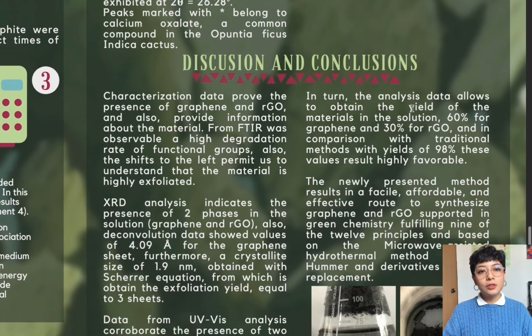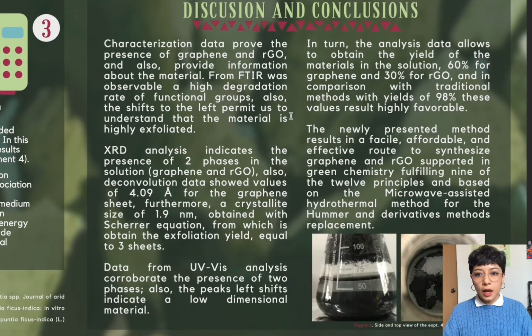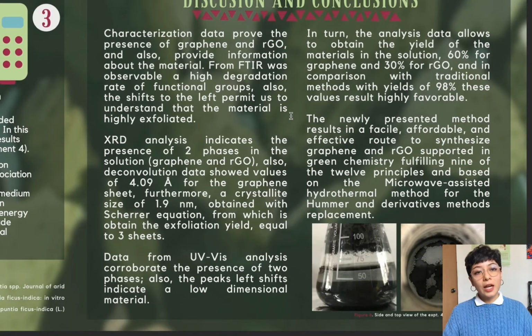Discussion and conclusions. Characterization data prove the presence of graphene and RGO, and it also provides valuable information about the material. From FTIR analysis was observable a high degradation rate of the functional groups, and the shift to the left lets us understand that the material is highly exfoliated. XRD analysis indicates the presence of the two phases in the solution.